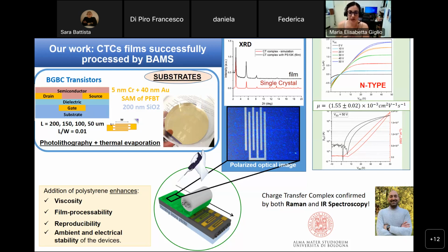So after that, basically, we can deposit the film by the technique, BAMS. And then in the end, we get a very homogeneous, crystalline film of charge transfer complexes. We performed X-ray diffraction, and we could see that there is a very good agreement between the experimental results of the film and the simulation of the single crystal, as well as the measurement of the single crystals. And then this is done by a collaborator of mine, Dr. Tommaso Salzillo in Bologna. They performed Raman and infrared spectroscopy, and they confirmed the presence of the charge transfer complex in the film.